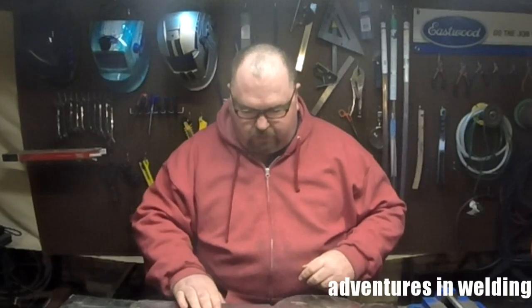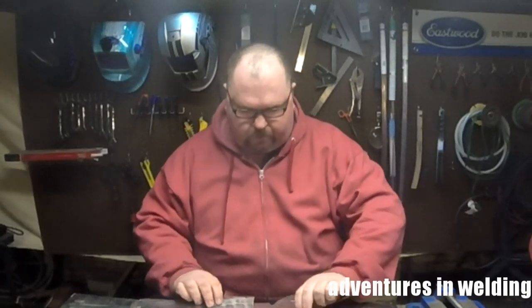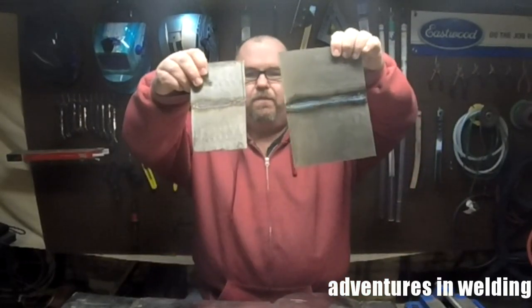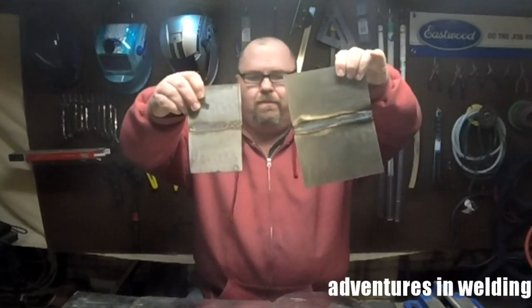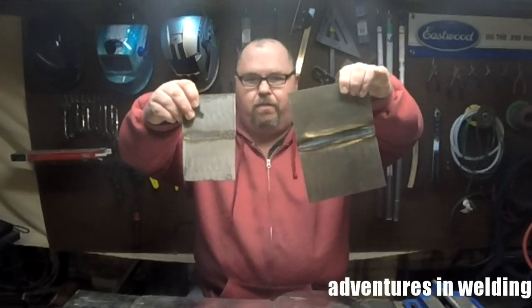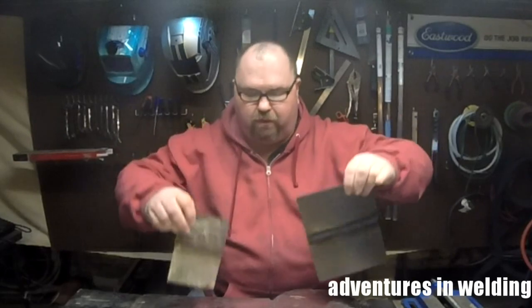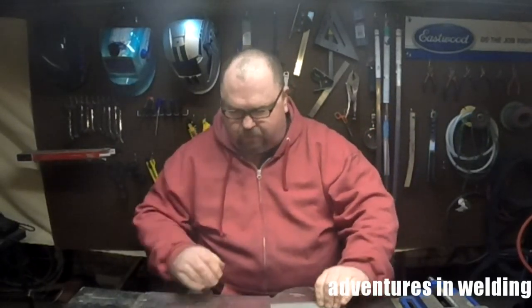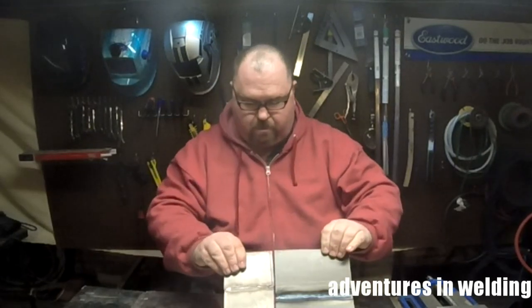Well, as you can see, folks, we've got our couple of nice autogenous butt welds in the stainless steel and in the mild steel. This is an excellent process to use if you're taking thin material. Both of these are about 18 gauge. Keep in mind this works only for steel and stainless steel. It does not work for aluminum because of aluminum's hot, short cracking tendencies.